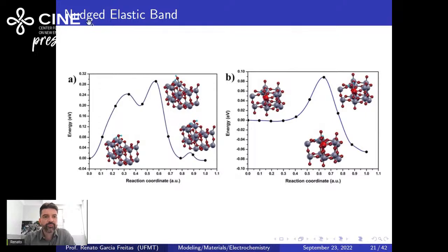At last, we performed some nudged elastic band, so NEB. We performed the several steps of reaction. In this case, we have the water absorbed onto the surface of titanium oxide, and here, titanium oxide iron doping, and it splits, one hydrogen absorbed on a titanium, and you have OH, which is released to the surface. We have OH dot, which is the oxidative species responsible for degradation. In this case, it was rhodamine.